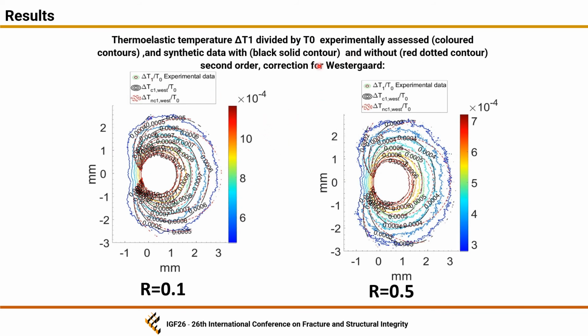In this slide, we can see the isopachic curves for experimental data and the curves of synthetic data obtained by the new formulation and the classic formulation, which are the red dotted contours. We can see that for the stress ratio of 0.1 there is a great agreement of the black solid contour, which represents the new formulation temperature variation assessed by using Westergaard, with the experimental data, and the same consideration can be drawn also for the stress ratio of 0.5.